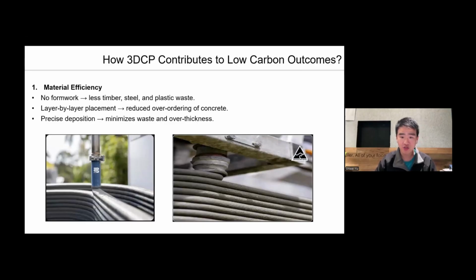When we talk about 3D concrete printing construction leading to low carbon outcomes, the first biggest factor is material efficiency. Because there's no formwork, we cut down heavily on timber, steel, and plastic waste. With layer by layer placement, we only use the amount of concrete that's actually needed, so no more over-ordering just to be safe. And thanks to precise deposition, the material goes exactly where it should, which avoids unnecessary thickness and reduces waste even further. Altogether, this means less material, less waste, and a much smaller carbon footprint.